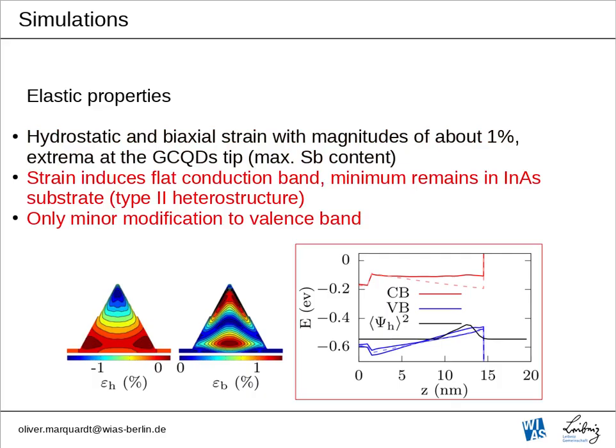On the right side, you see the band structures. The dashed lines are the ones unmodified by strain, so only from the bulk parameters. And the solid ones are the ones that see modifications from strain and deformation potentials. If you look at this plot, you see the conduction band, the red line, which has a minimum on the left side. The left side of this plot is essentially the indium arsenide substrate. And then the band throughout the quantum dot is pretty much flat due to modifications from strain. For the valence band, you see that the maximum is pretty much at the tip of the quantum dot, and modifications due to strain are very, very small, which gives us then a type 2 heterostructure with the electrons being somewhere in the indium arsenide substrate, and the hole, here indicated as a black line, will be somewhere in the tip of the graded composition quantum dot.